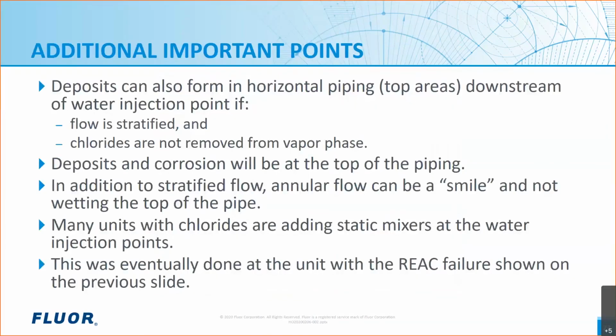Okay, some additional important points about ammonium chloride corrosion. The deposits can form in horizontal piping, and it always forms in the top. So that's almost a key clue that it's ammonium chloride corrosion that's occurring, when the corrosion is at the top of either piping or the tubing. So we can form deposits in the horizontal piping downstream of the water wash injection point if the flow is stratified and the chlorides have not been removed from the vapor phase. So they'll be at the top of the piping.